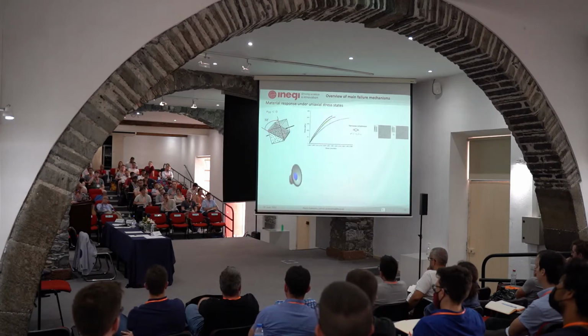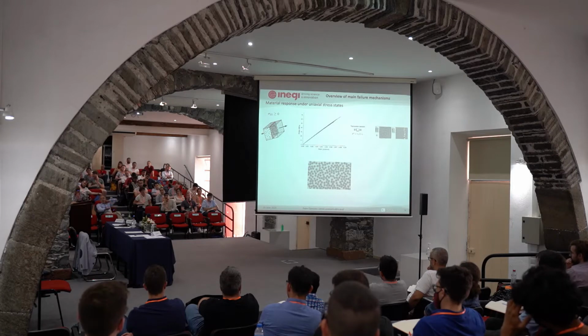At the micromechanical level, we can have some... In this case, we didn't simulate any void, but we could simulate some voids and have the crack starting from a different position. Here it's from the interface. But also here it's important how to optimize interfaces and coatings. Exactly. Because obviously, if you resin sees cracks at 8,000 or 9,000 microstrains, there you have their own interface and cracks initiated at 6,000 microstrains or 4,000 microstrains.